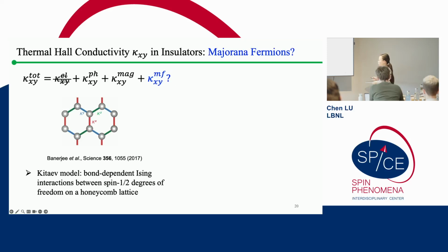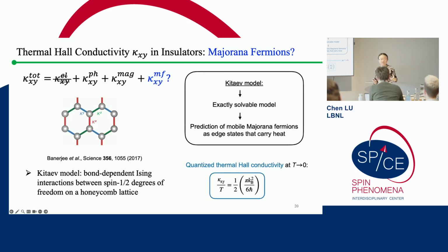The reason why this Kitaev model is so important, and generated a lot of experimental motivation for thermal transport studies, is because theorists predicted, in this exactly solvable model, that if you have a Kitaev spin liquid, you will have mobile Majorana fermions which act like edge states that can carry heat and give you a thermal Hall effect. And what is more important is that this thermal Hall effect has a special feature: the half-quantized thermal Hall conductivity has an exact value. So this theoretical prediction has triggered a lot of searches in experiments to look for this kind of signal.